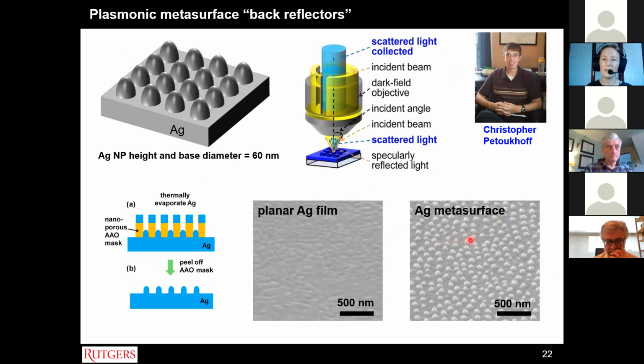And he created these silver nanostructured back electrodes using thermally evaporated silver through a nanoporous alumina on silver. And then we peeled off the anodic alumina and we created these particle-based silver films.